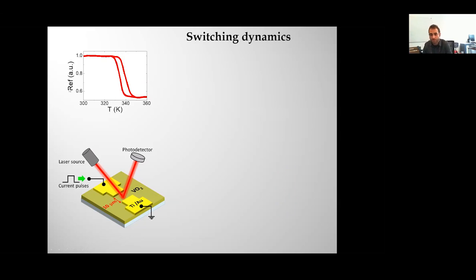in a particular area. So what we did is we modified the experimental setup to be able to focus a laser down to a 3 micrometer spot here in between the oxide gap. And then we use a photodetector to measure reflectivity, and we measure the time-dependent reflectivity to measure the metallic phase fraction as a function of time when we send a pulse of current.